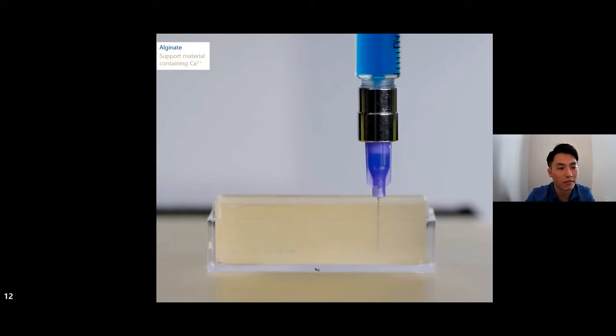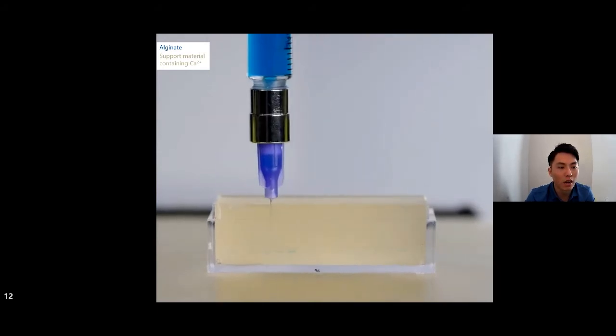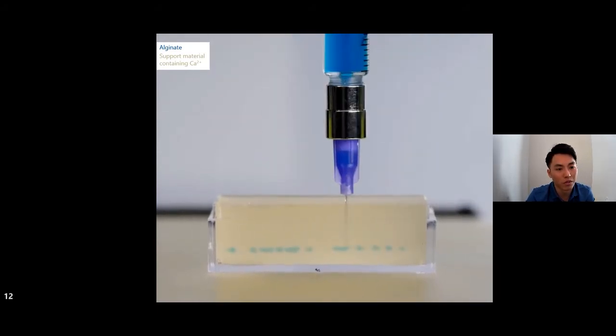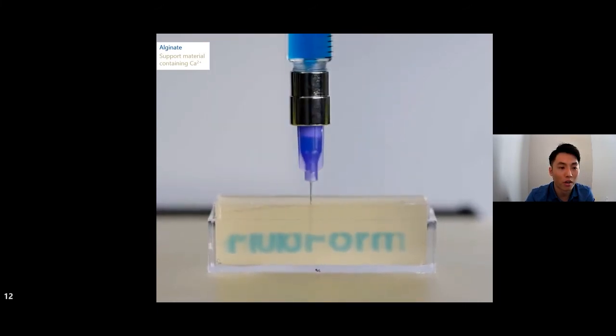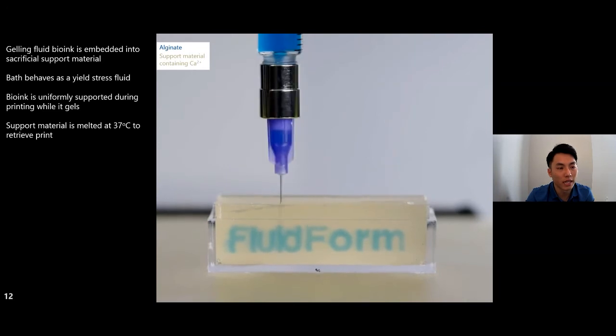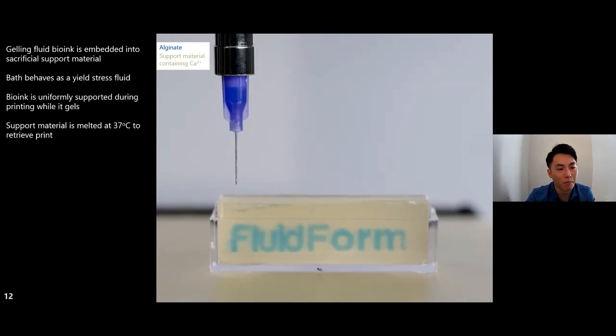In this video that I'll show here, we have a syringe loaded with a blue ink, alginate, which a lot of you might be familiar with. And then also we're printing into a support material containing calcium ions. So calcium ions help facilitate alginate gelation. And so as we're depositing our alginate into our support material shown here in the container in yellow, we're simultaneously cross-linking and gelling the alginate in place to create our three-dimensional construct.